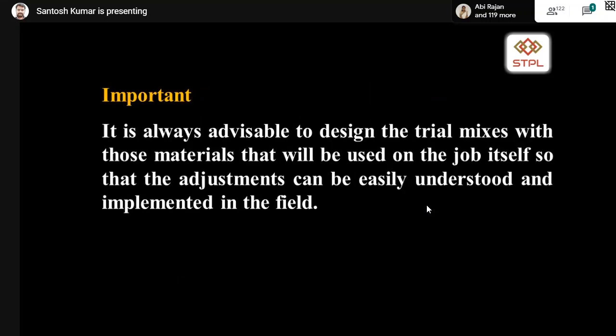One thing I want to highlight here is, it is always advisable to design the trial mixes with those materials that will be used in the job site, so that the adjustments can be easily understood and implemented in the field. If you take a practical national highway project, the length of the project will be around 100 km, but the mix design will be 1 for PQC. It should not be the same. Whenever you change the source of the aggregates, the mix design should vary. So that is more important.